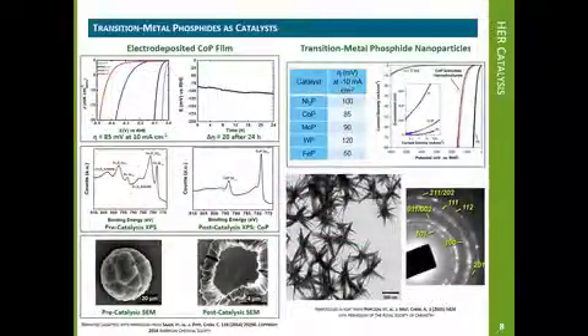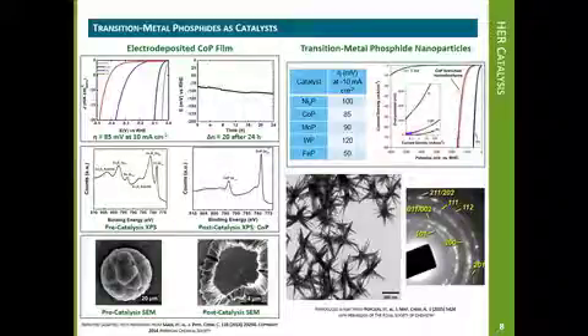Further dramatic reduction in the HER overpotential has been achieved with transition metal phosphides. Nanoparticles of cobalt, molybdenum, and iron phosphide are now capable of sustaining 10 milliamps per square centimeter at overpotentials below 100 millivolts. This remarkable performance has stimulated further interfacial characterization of these materials in preparation for their integration to a scalable solar fuel device.